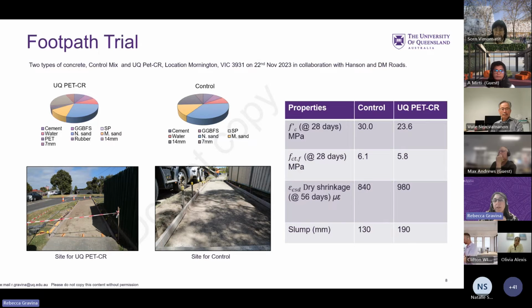So you can see here the two sites for the different types of mixes, our control mix plus the mix with the recycled material content, so the crumb rubber and the PET, and also the properties on the day from the concrete that was supplied in terms of the compressive strength, flexural tensile strength, drying shrinkage, and the slump.